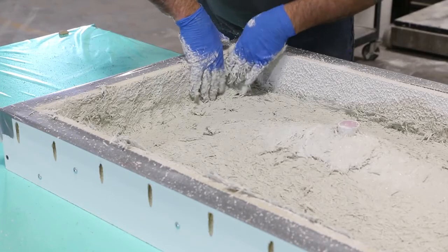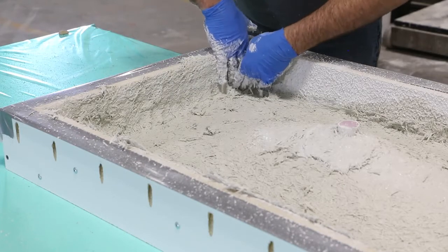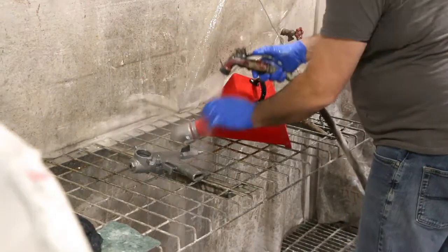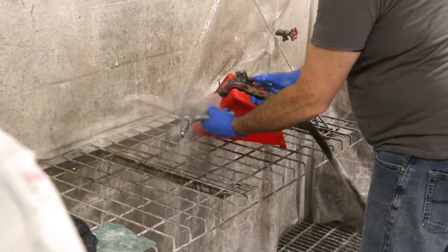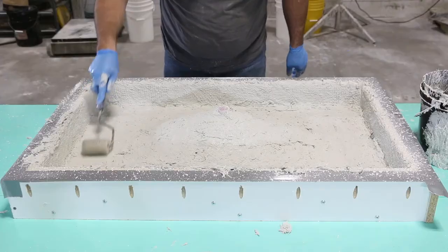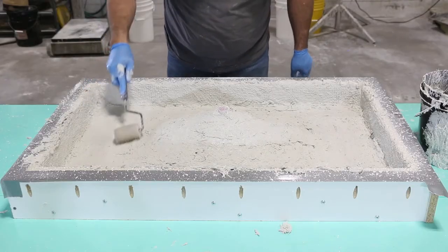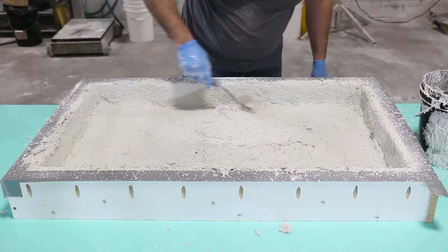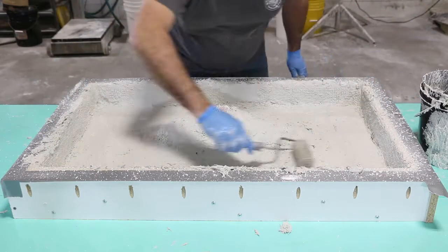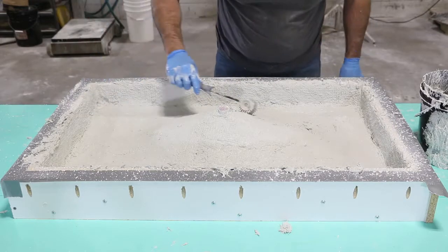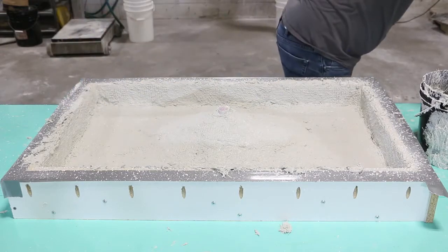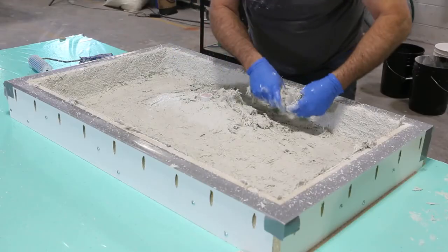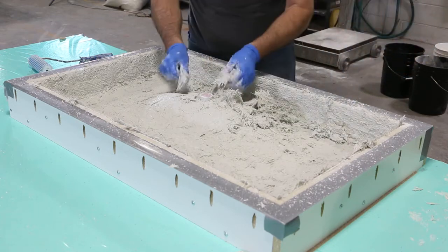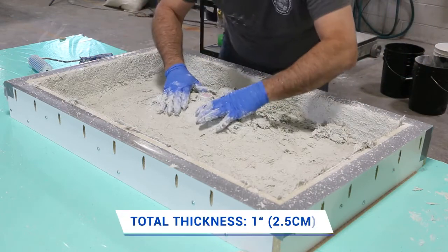Once the first layer of backer has been applied, now is a good time to clean the hopper gun thoroughly, since this material will keep the face from drying too fast. Compaction rollers are used to press the material flat, compacting and aligning the fibers, which also removes excess air. Continue adding more backer material in layers while compacting until full prescribed thickness has been achieved.